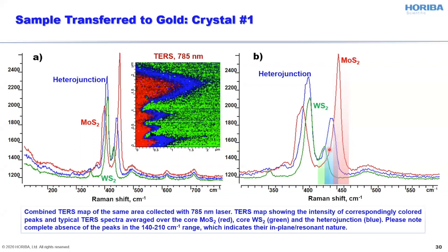Earlier this year, there was a nice paper published in Nature that showed that with non-resonant excitation in gap mode TERS, we are sensitive mostly to the out-of-plane modes. And when we have resonant excitation, we can also be sensitive towards the in-plane vibrations.